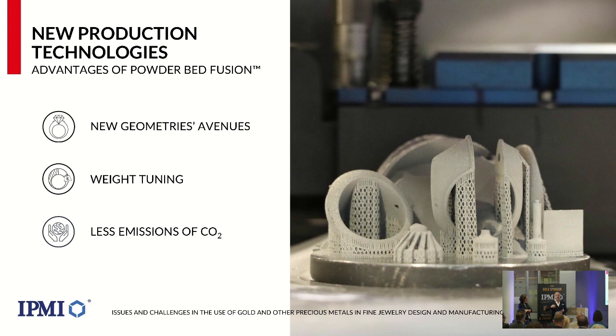On the other side, you have something that is too heavy, maybe 70 grams, 80 grams. And then for wearability reasons, you need to drop to 50 grams. And when you drop to 50 grams, you have two choices. Either you make it in separate parts and then you assemble, but when you assemble, you have the soldering line, and this is an issue in high-end jewelry. Or you make it hollow through that technology. And the emission of CO2 is really much lower.